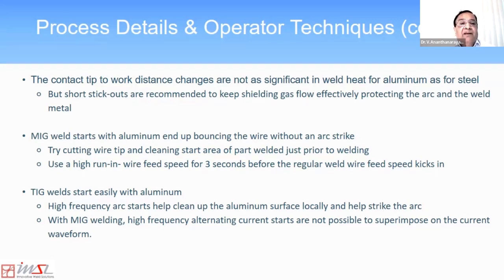And also use a high run-in wire speed initially at the weld so that you get good weld starts before the regular wire feed speed kicks in. And when you're doing TIG welding of aluminum, high frequency arc starts help clean up the aluminum surface locally and help strike the arc well. And with MIG welding, high frequency alternating current starts are not possible to superimpose on the waveform.